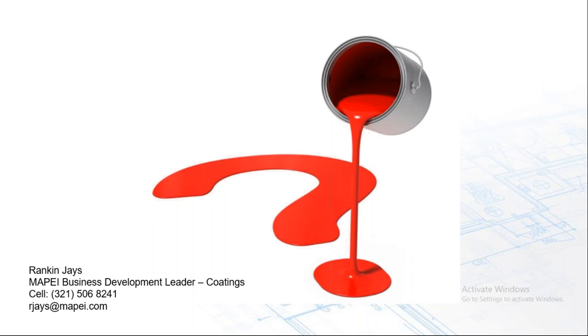Yes, crack bridging is a function of elongation and tensile strength. Elongation being the important one, tensile strength being the force required to create that elongation. So the tests are different, but they are related, I should put it that way.